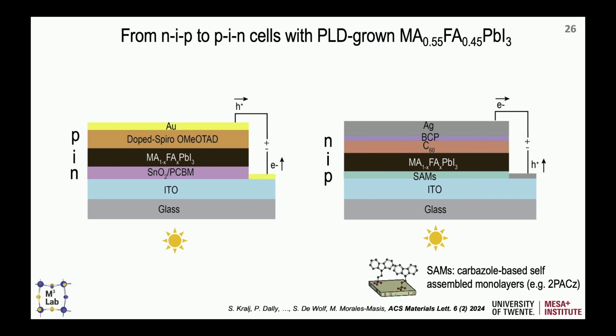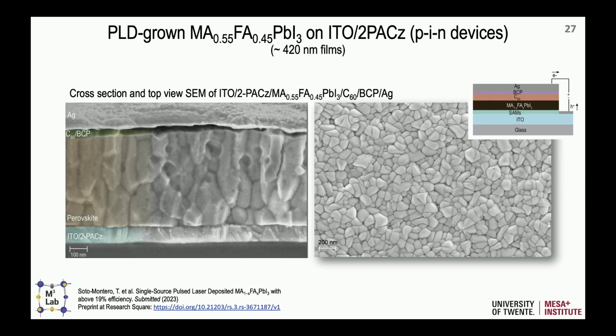We did not develop this, but we basically used the standard, let's say, device structure from many groups, which nowadays is a lot based on these self-assembled monolayers. So they are carbazole-based molecules that have a dipole moment that allows for the extraction of holes. So we basically took this as a substrate, so the ITO with the self-assembled monolayers, and then Tatiana went back to the lab to develop the same PLD recipe, but now in this type of devices.